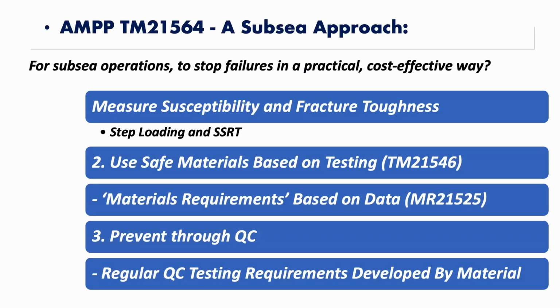Okay, so in our case, we're measuring the susceptibility and doing our fracture toughness evaluation using two main methodologies. One is the step loading and the other is SSRT. They both have advantages and disadvantages, but both of them give you a lot of data in a fairly quick time frame. One of the things that we've had to come together to agree on, though, is if you're doing slow strain rate testing, there is definitely a sensitivity to your strain rate. And so we're settling on only specific strain rates so that we can eliminate some of that variability.